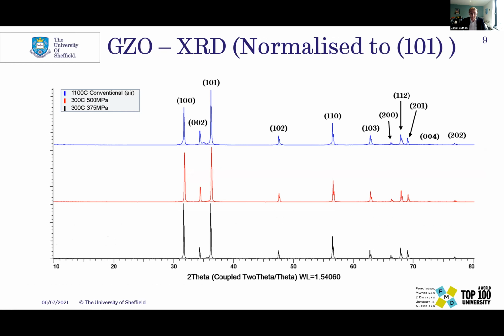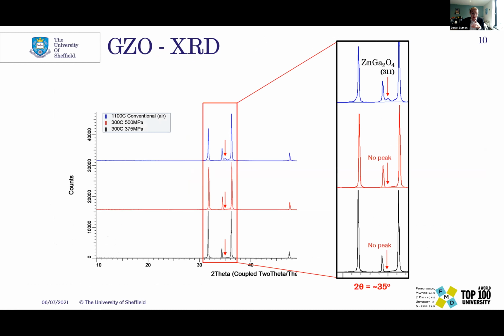Next slide, please. The GZO showed pretty much, so the top is conventional and the bottom two are cold sintered at different conditions. You can see in the top left, they're very similar to zinc oxide. However, the conventional shows the presence of a zinc gallate, which is a well-known spinel structure that tends to form. There's the debate on whether it's actually useful in the material. It's got a very different band gap and conductivity to zinc oxide.